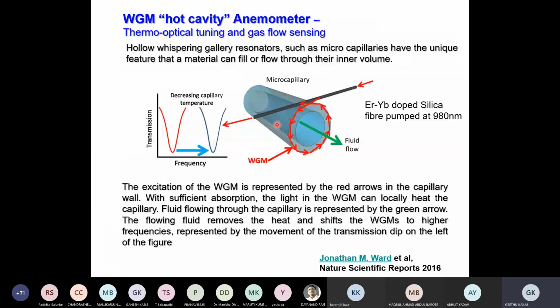And there are different works that are going on. For example, here is a capillary, and this is a glass capillary. Glass is doped with erbium, ytterbium, rare earth material, and it is excited with a 980 nanometer laser, and some fluid, it can be gas or liquid, is flowing through the capillary, and the excitation of WGM actually locally heats this capillary, and depending on the heat, the movement of the fluid is controlled, and the fluid flow can be completely monitored by monitoring the light that is propagating through this fiber.